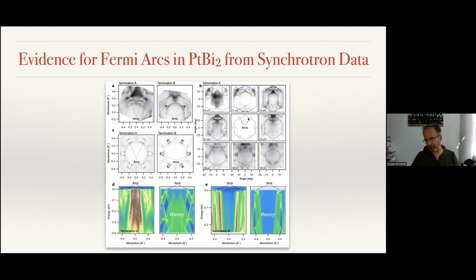So the arcs are situated at these positions, exactly where the theory predicts them. And even at higher photon energies, where the resolution is worse, one could still probably track the arcs at all the other photon energies which we studied. And this is important because when the photon energy changes, the three-dimensional structure changes, because we cut at a